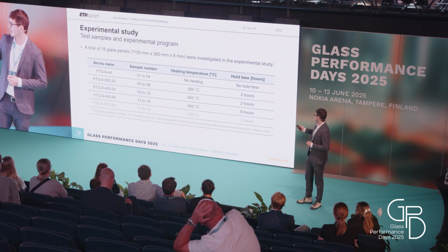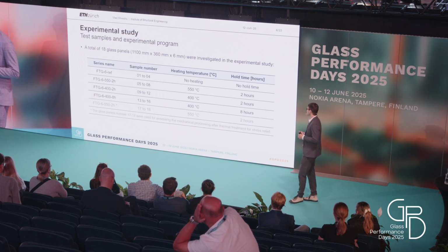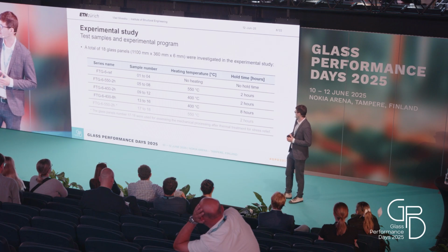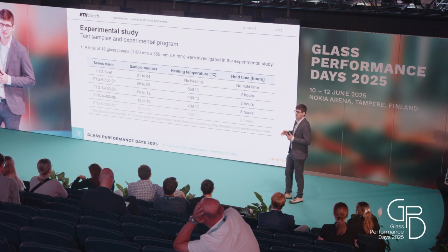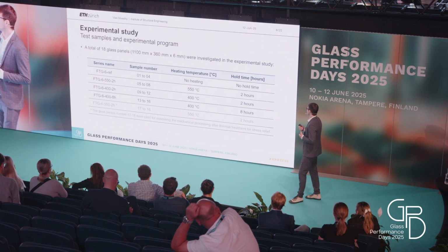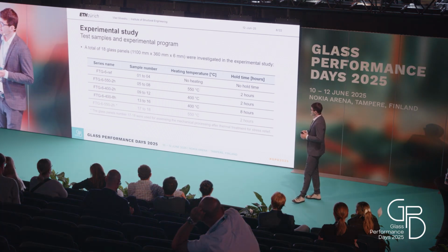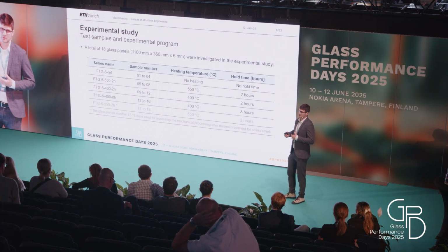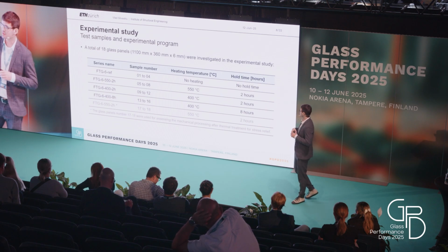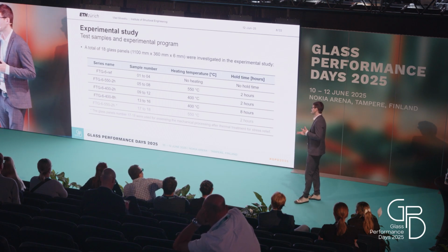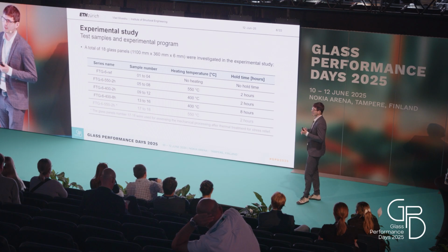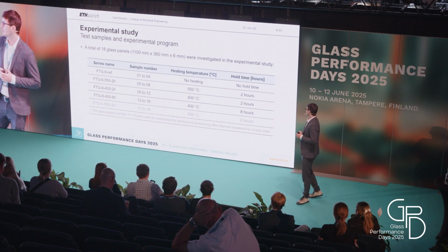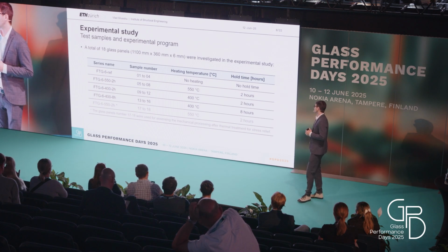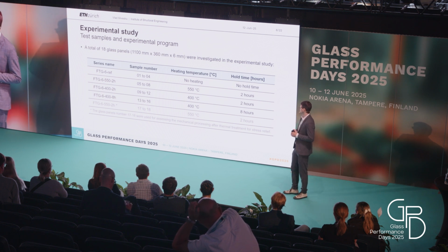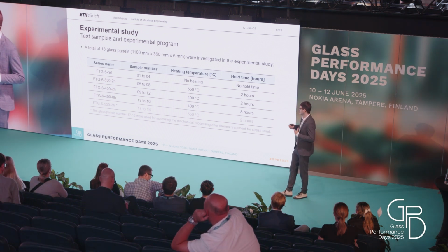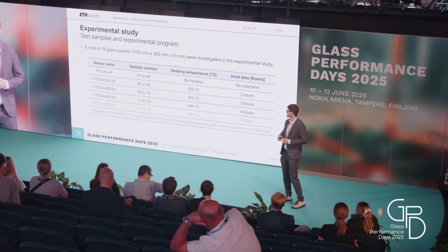And I had some reference series without any heat treatment, a series where I heated it at 550 degrees, which is approximately the annealing point, for 2 hours. And then I also wanted to look what happens if I treat it at lower temperatures. So I chose 400 degrees, which is somewhere between the 550 and the 290 of the heat soak test. And here I also looked at different hold times, so 2 hours and 8 hours, to see what the difference is if we increase the hold time.